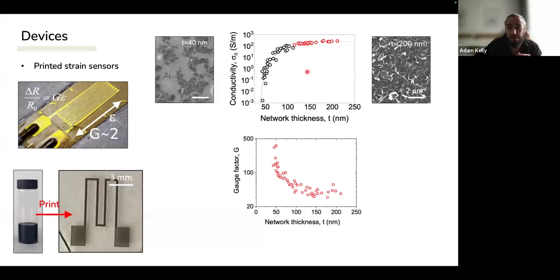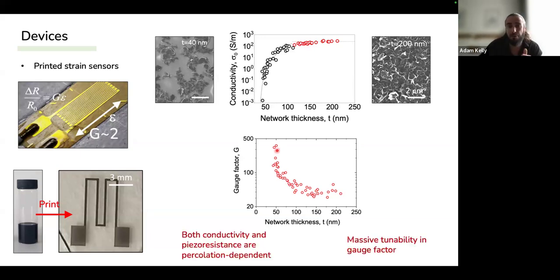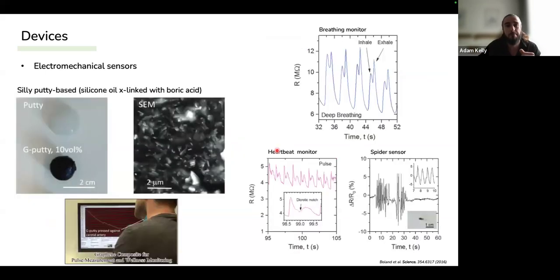Now, what we found was interesting was that this gauge factor value shows inverse behavior. So at very, very low network thicknesses, when this is discontinuous, we get extremely high gauge factors up in the hundreds. Okay, so this is far beyond what you can achieve with a metal. So what this means is simply by tuning the thickness of our network, the conductivity and the piezoresistance themselves can be tuned over a very, very wide range.